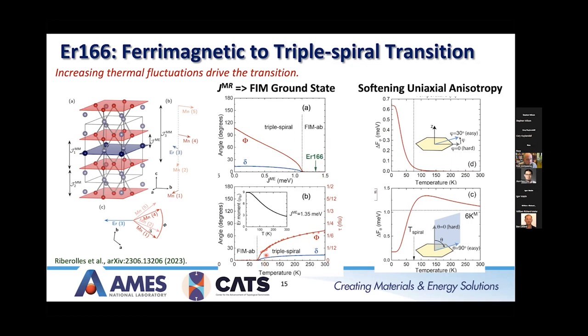If we overplot here, we have the calculated angles phi and delta as a function of temperature using the Hamiltonian I showed you before within the mean field approximation. We lay over what we found from the antiferromagnetic propagation vector, and we get very good agreement between the two. And then we were also able to show that driving this spin reorientation with increasing temperature is increasing thermal fluctuations of the erbium moment. So the fluctuations increase, the ordered erbium moment decreases, and eventually you get this spin reorientation.